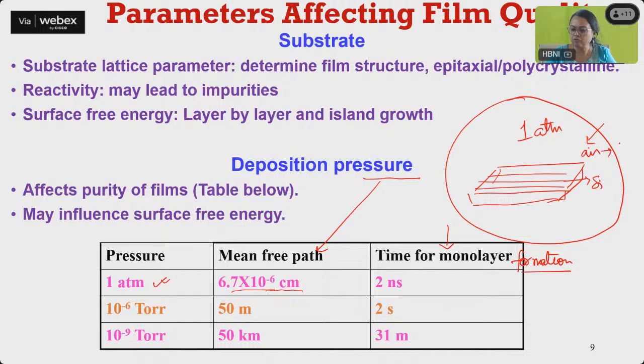So in air, what do we have? We have oxygen, argon, nitrogen, and all those things. So these atoms will start sitting here, and within 2 nanoseconds, a single atomic layer will get formed on this silicon. So the surface of your silicon substrate will not remain as silicon. There will be one monolayer formation within 2 nanoseconds, which if we don't want, then we should have a better pressure.